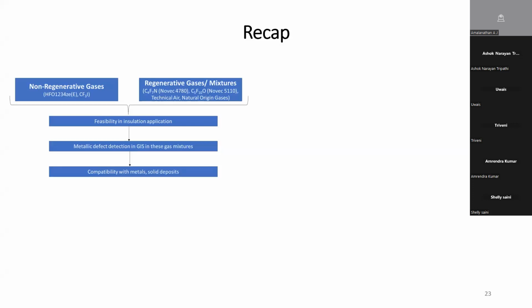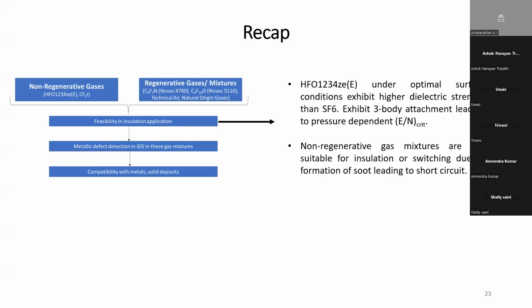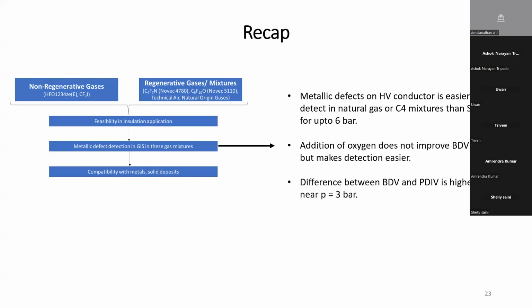So we studied the non-regenerative and the regenerative gas. From the feasibility, definitely HFO does exhibit better insulation than SF6, but then it shows the three-body attachment as well. But the non-regenerative gas mixtures are really not suitable for insulation or switching because they have soot formation, which can lead to short circuit. Metallic defects on HV conductors are easier to detect in C4 or natural gas than SF6 up to 6 bar.